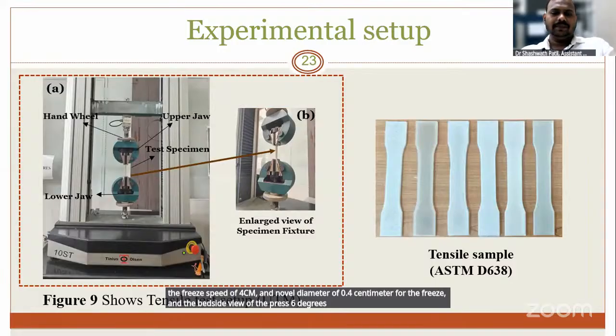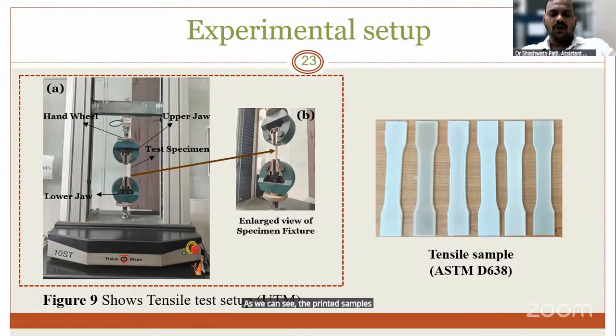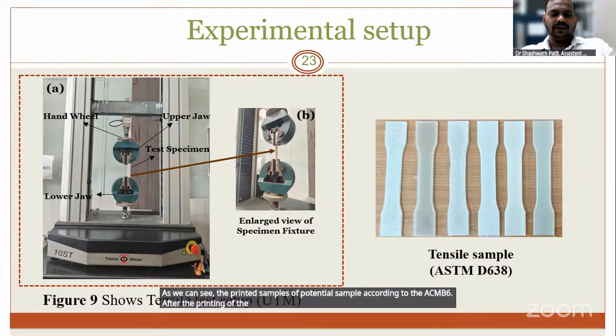As we can see, these are the printed tensile samples according to ASTM D638. After printing the samples, we are doing the tensile test using this UTM. As you can see from this image, we have placed our sample in a vertical position and clamped it in the UTM machine.